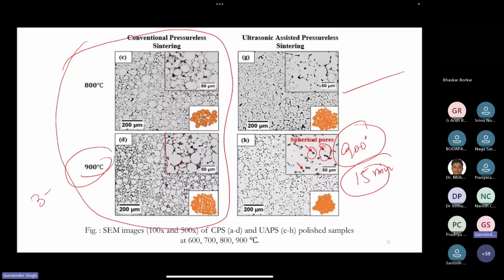Now you are getting spherical pores. If you remember the sintering mechanism, spherical pores signify this is the last stage of sintering. So your density is around 99%. You can process this part further. It will give you some density, but it will be a very slow process. You can't get 100% density here.